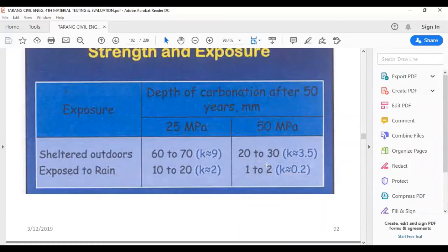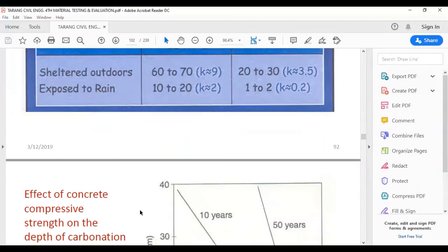So depth of carbonation versus strength and exposure. So if it is sheltered but outdoors, then depth of carbonation after 50 years in mm, for 25 MPa it is 60 to 70, and for 50 MPa it is 20 to 30. And when exposed to rain, you can see it significantly reduces the depth of carbonation.